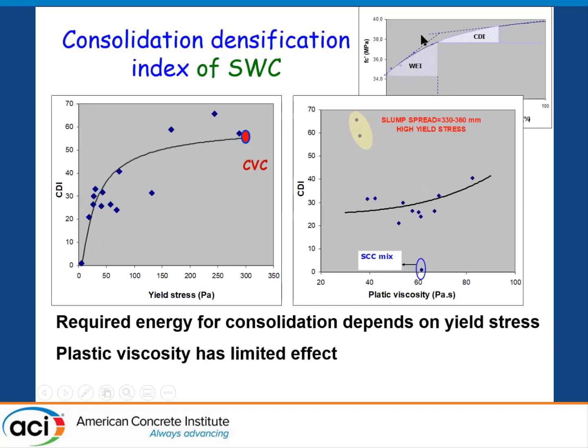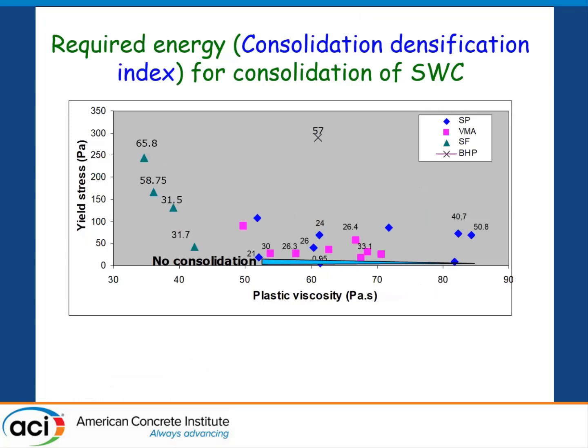And then in terms of the consolidation densification index, which is the last part that contributes to strength gain, we see that it's also dependent very much on yield stress and not so much dependent on plastic viscosity. So we decided to put all the data on a yield stress versus plastic viscosity curve. And this is the SCC. And what is shown in blue over here, it really reflects this consolidation densification index, which is the energy that is calculated during that part of the consolidation.